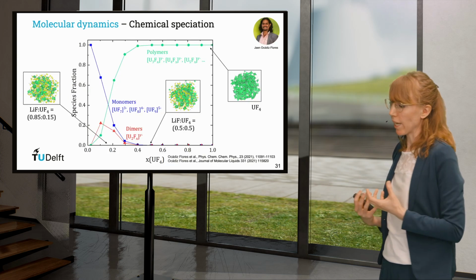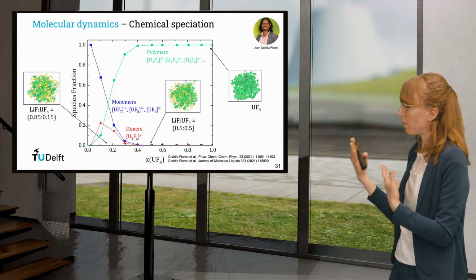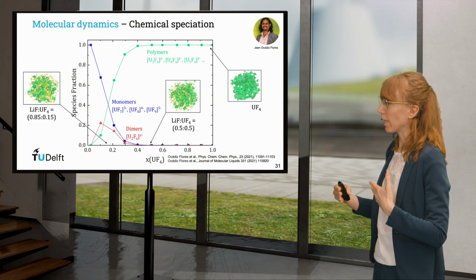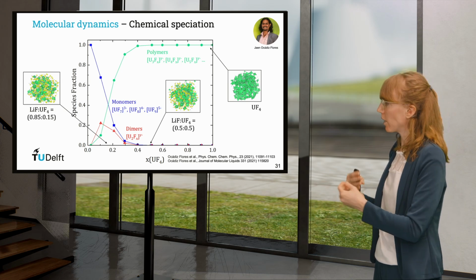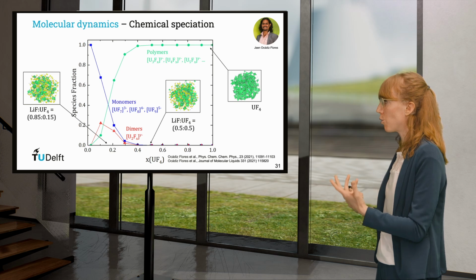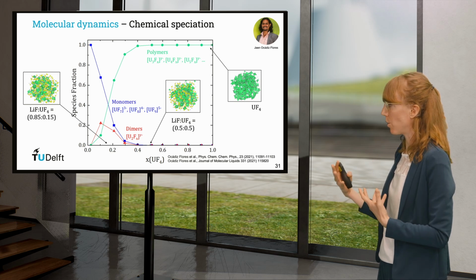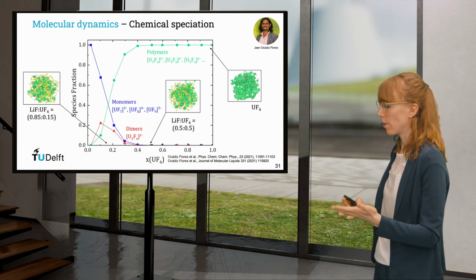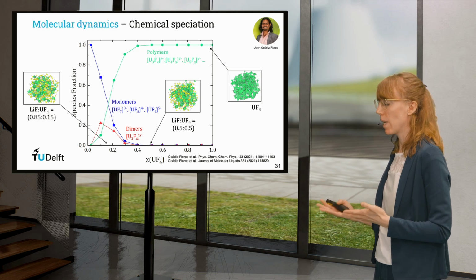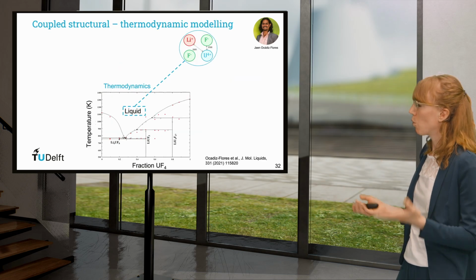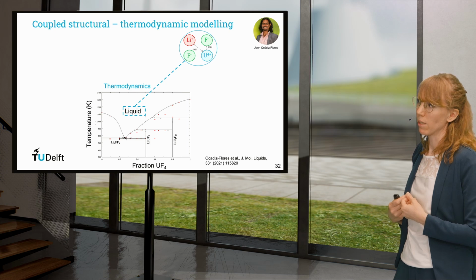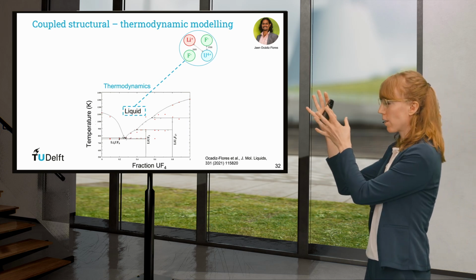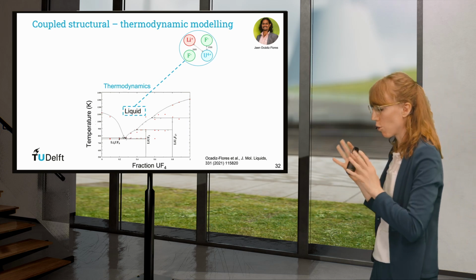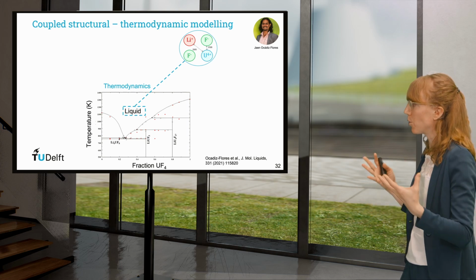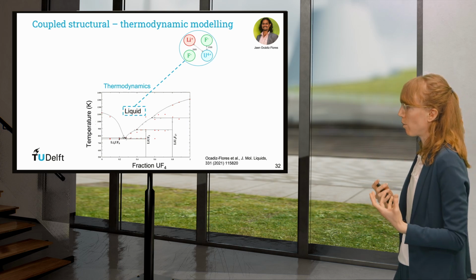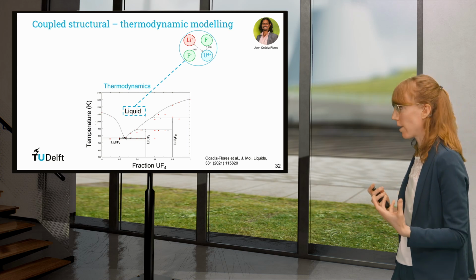And with that, we can know what the so-called chemical speciation looks like. So we can get a picture from the molecular dynamics on the formation of monomers, dimers, trimers, polymers as a function of temperature and as a function of composition. And all of this information we then use for the modeling. You remember, this is the quadruplet you see on the screen. The quadruplet is the widely used methodology to do this thermodynamic modeling, and I'd say it's very effective.